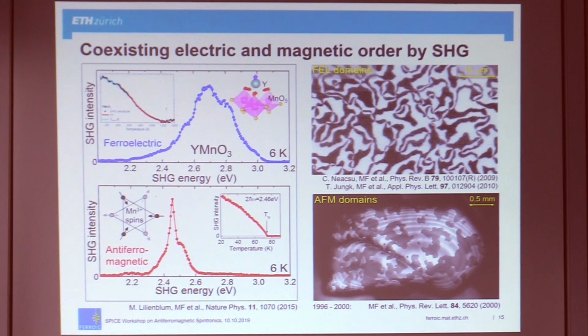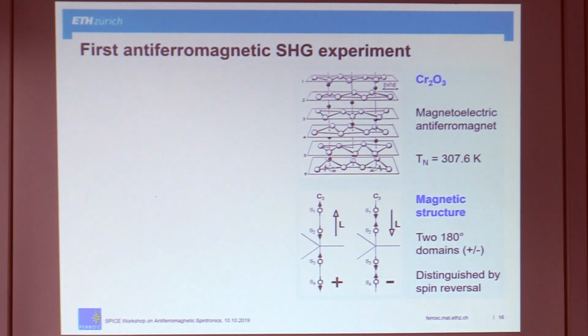What is nice is it's an optical technique, so you can now take this light at this frequency, for example, and image your sample onto a CCD camera, and then you get distributions of antiferromagnetic domains very easily. And these are 180 degree domains, so the type that is most difficult to find or to detect. You just image it a few minutes, and then you have a picture. Here is the oldest example of such a picture. So chromium oxide again with this up, down, and down, up, domain states.